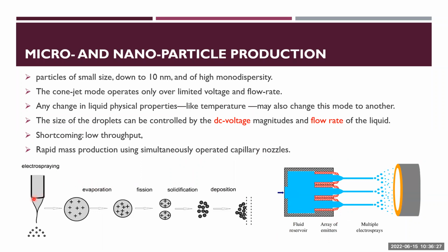When we are talking about organic solvent, the technology used to make particles is basically evaporation. You spray the particles, and on the way they disperse because of the electrical repulsion. Then the solvent evaporates and you receive particles deposited on, for example, aluminum foil. Then you can scrape them and get ready nanoparticles in a solid state, not like in other technologies where you get the particles in a solution or suspension and you need to centrifuge and separate them.